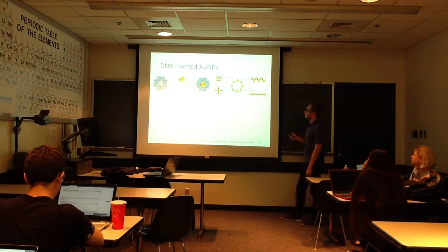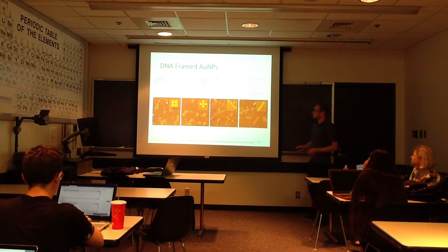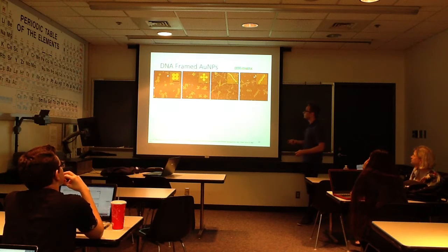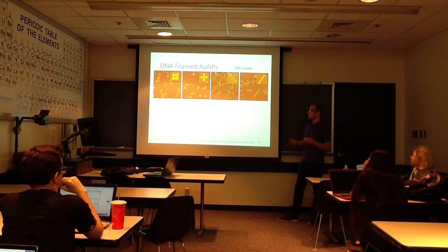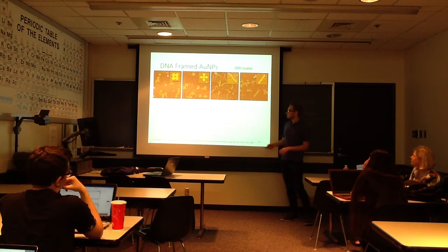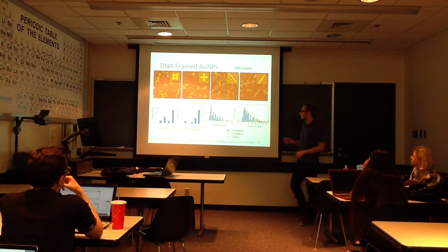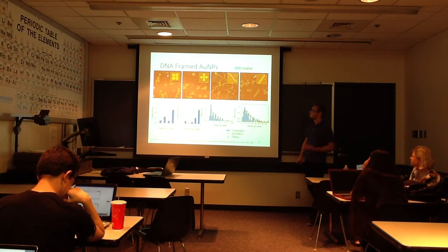Depending on how you orient them, and what sort of DNA nucleotides or base pairs you use to connect on each side, you can make clusters or cross sections or basically different types of shapes. If we look at this in an AFM image, atomic force microscopy, we can see that these show up quite nicely. Generally you just throw these in with the blueprints or each individual part, and they auto-assemble or self-assemble over time without any real issues. You can see different particles per cluster and compare this experimentally to simulation and theory, and it comes out quite appropriately to both and turns out quite nicely.